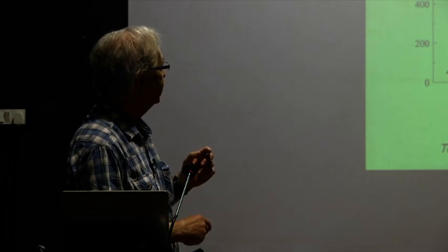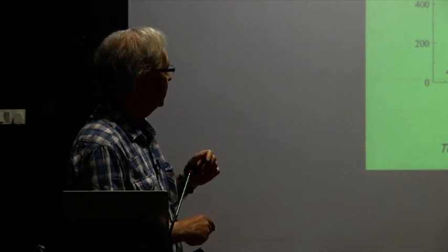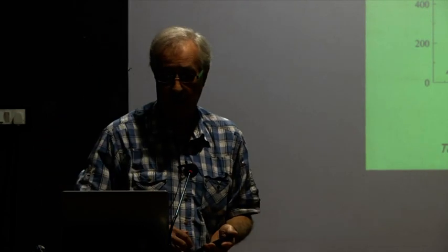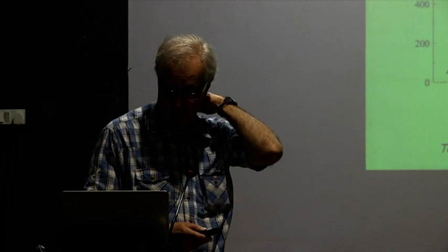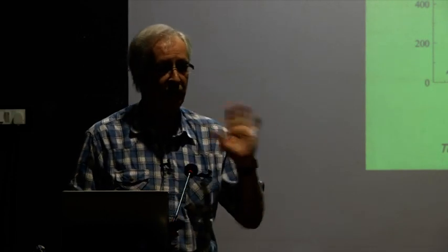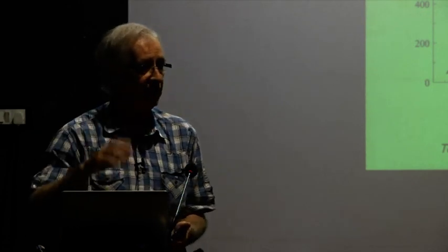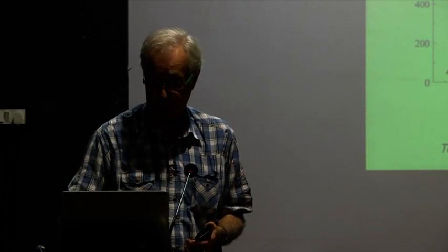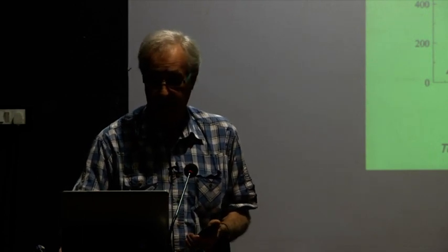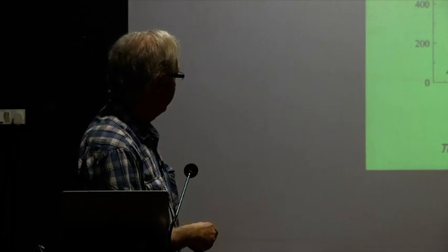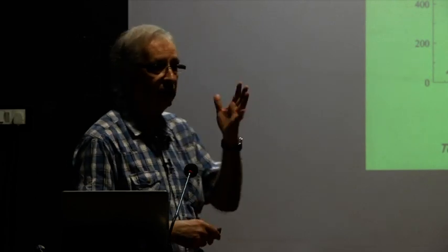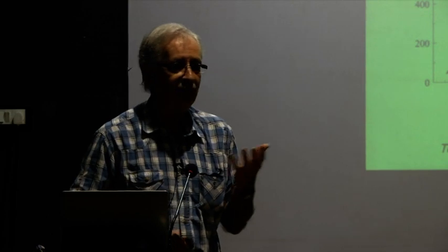And then when you start adding gallium, aluminum, or whatever, the electron concentrations start dropping, and the martensitic transformation temperature drops with decreasing electron concentration. Okay, so this is what we have at hand. So moving around the electron concentration, choosing correct compositions, you can play around with martensitic transition temperatures. By the way, this shaded area over here lies around 200 to 500 Kelvin, which is a technically meaningful area.